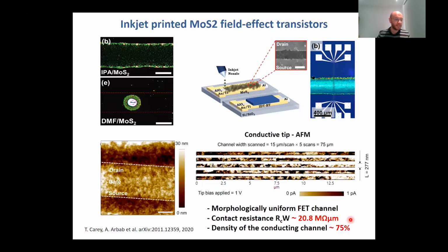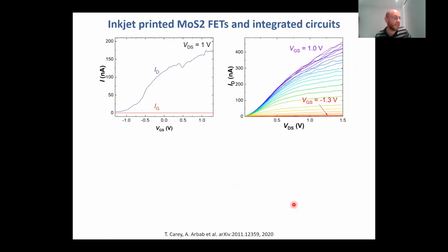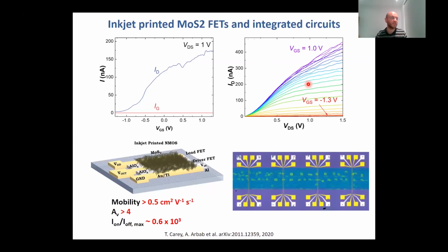And then this, combined with the morphological uniformity, actually allows us to have very nice FETs that are modulating, showing a typical N-type behavior of MoS2. Here you can see that, with relatively small VGS, we can modulate the ID. And also we can see that the conductivity, the resistivity, is actually modulated thanks to VGS with the typical FET behavior. So this is extremely interesting because we can also extend to integrated devices, fully printed integrated devices, by printing